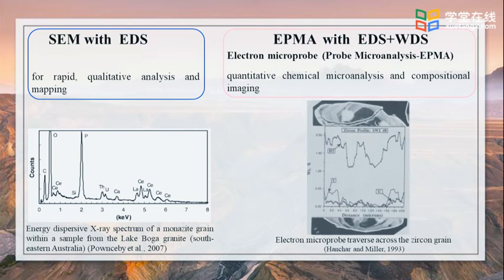As shown in the right figure, the electron microprobe traverse demonstrates that not only do the backscatter electron image and CL images reveal detail regarding different regions within the zircon, but also that the concentrations of hafnium, yttrium, and uranium vary considerably within the backscatter electron and CL revealed regions.